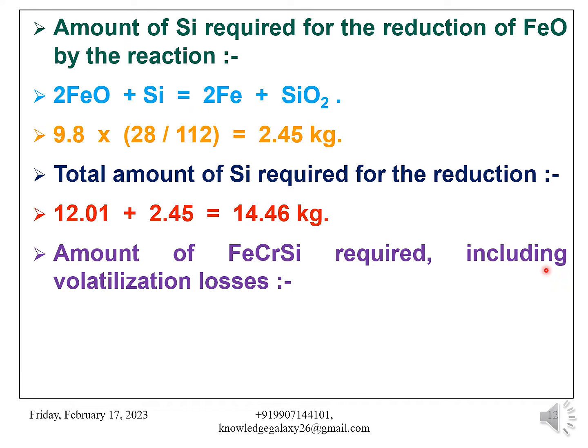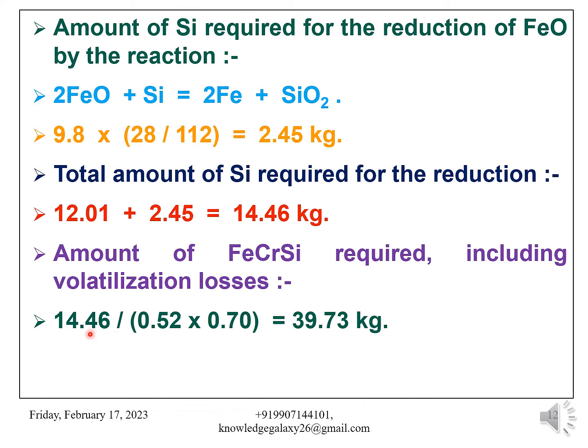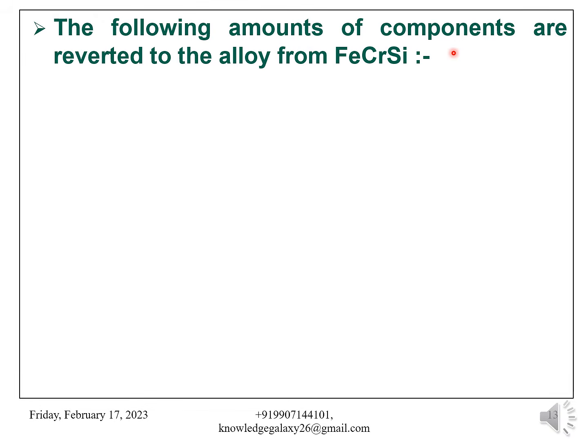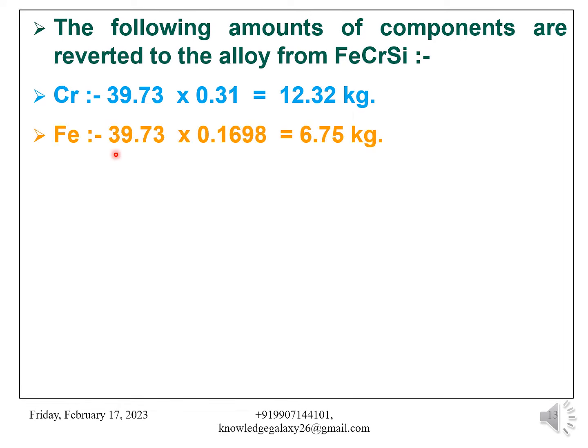Amount of ferrochrome silicon required including volatilization losses is calculated as 14.46 / (0.52 × 0.7) = 39.73 kg. The following amounts of components are reverted to the alloy from ferrochrome silicon. Chromium: 39.73 × 0.31 = 12.32 kg. Iron: 39.73 × 0.1698 = 6.75 kg.